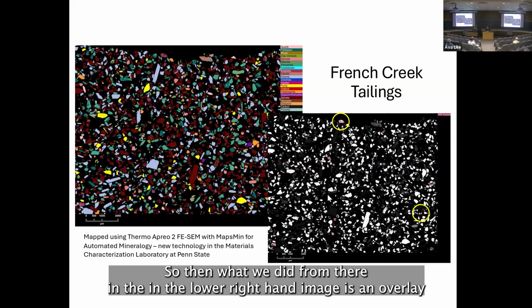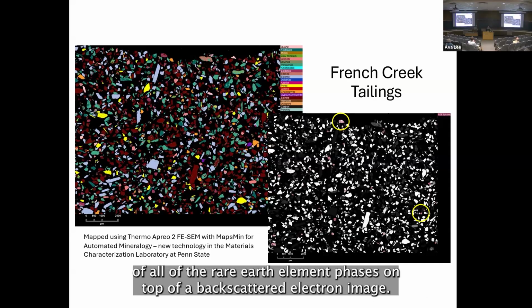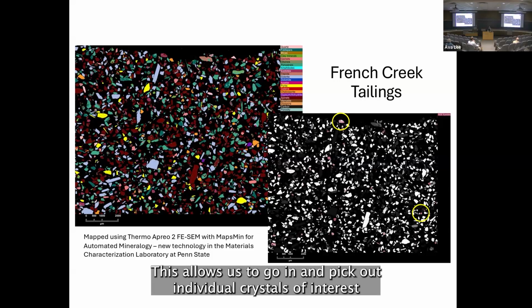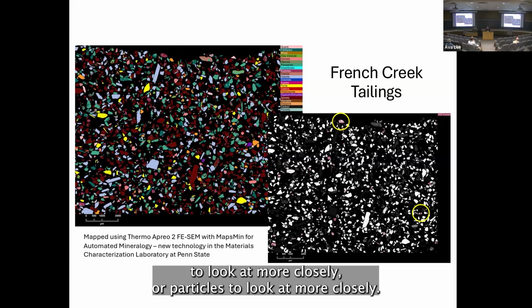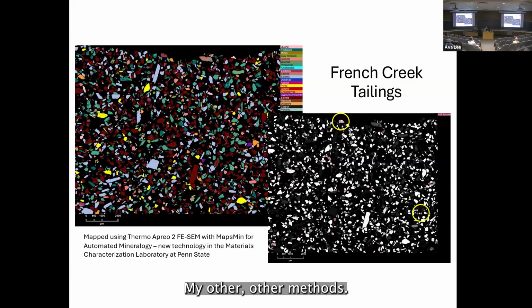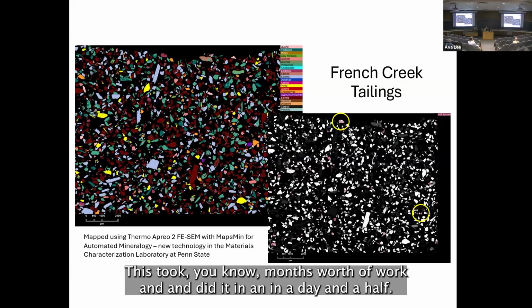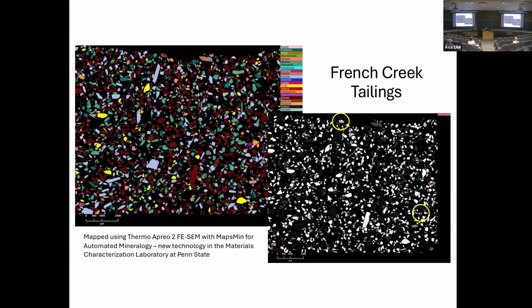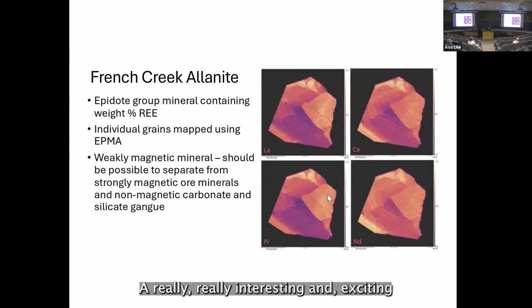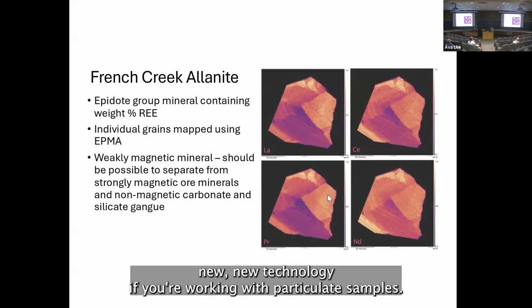So then what we did from there, in the lower right-hand image, is an overlay of all of the rare earth element phases on top of a backscattered electron image. This allows us to go in and pick out individual crystals of interest, or particles, to look at more closely by other methods. This took months' worth of work and we did it in a day and a half. Really, really interesting and exciting new technology if you're working with particulate samples.